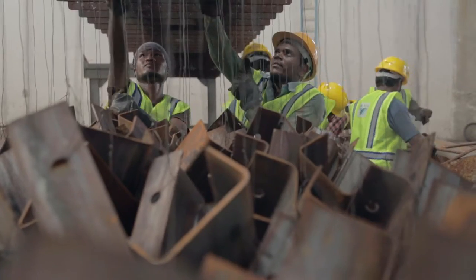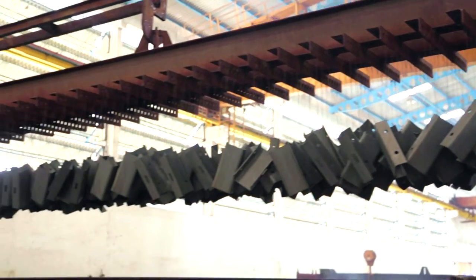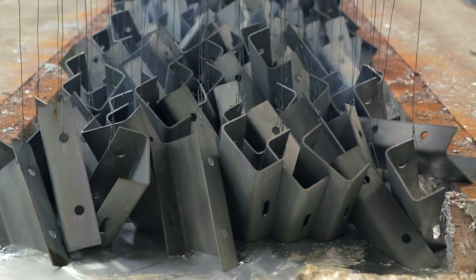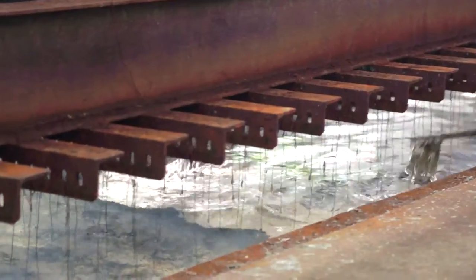The most important process is galvanizing. Galvanizing, as generally required by clients or by IS standard, is 550 grams per square meter, which is 77 microns. But sometimes it is required at 610 grams per square meter.